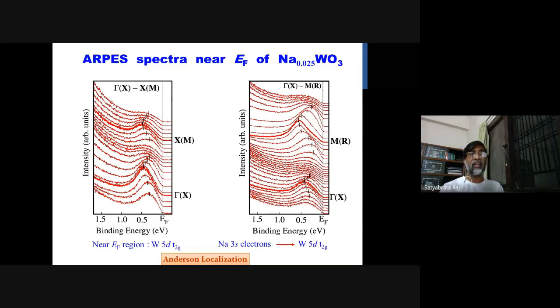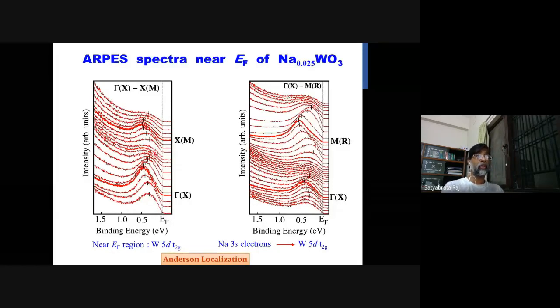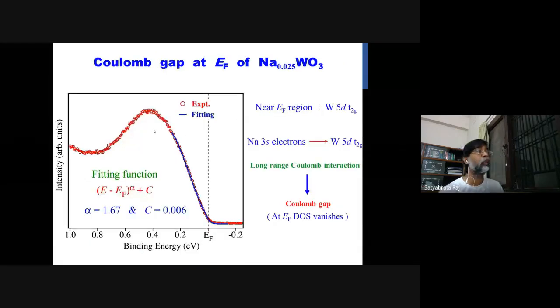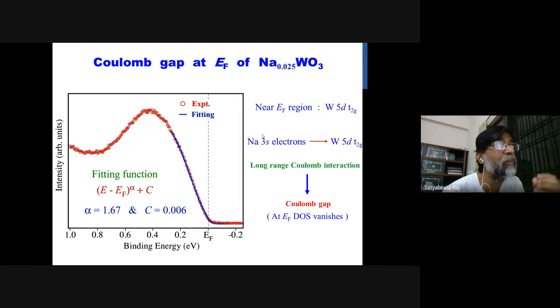So our conclusion is because of the Anderson localization, though the strong localization is not too strong to destroy this dispersion, all these states are almost localized, and as a result, you have a Coulomb gap, a soft Coulomb gap originating at the EF, and as soon as you go a little bit away from the EF, your density of states evolves, whether it's a Coulomb gap or a non-Coulomb gap. And Coulomb gap only develops when there is a long range Coulomb interaction, and that can be tested if you fit the density of states with E to the power alpha, and if your alpha is 2, then we can say that it's Coulombic type. So if our fitting says that it's close to 2, so we say that this is a soft Coulomb gap